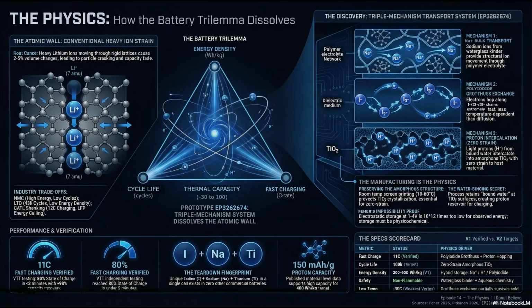And finally, that leads to the third conflict of the trilemma. Cycle life versus fast charging. The heat, the SEI scar tissue, and the dangerous metal dendrites. Well, protons simply do not decompose the electrolyte to form a solid electrolyte interphase layer in this specific system. And crucially, they do not plate out as a hazardous solid metal the way lithium does. You literally cannot grow a proton dendrite. Oh, you can't. That conflict is entirely erased. It's incredible. By changing the charge carrier from a heavy lithium bowling ball to a tiny proton marble, and by changing the host material from a rigid Jenga crystal to an amorphous sponge, the trilemma isn't just mitigated with clever engineering. It's dissolved at the foundational physics level.